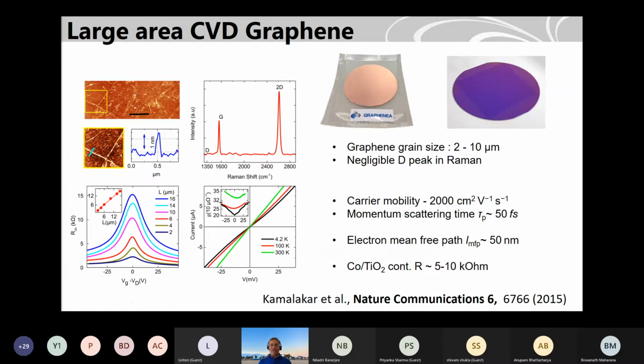You know graphene has a Dirac band structure. When you apply a gate voltage, you can go from the electron-doped to the hole-doped regime. This is the resistance of a graphene channel versus gate voltage, and you see such Dirac-type curves. It's called a Dirac curve because it has a maximum when you reach the Dirac point. Below this Dirac point, holes are the carriers, and above that, electrons are the carriers.